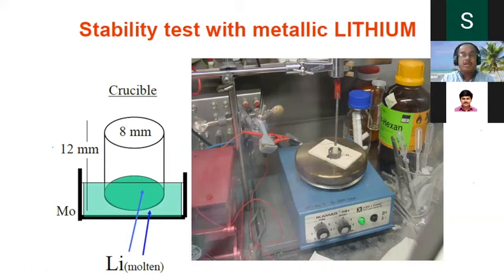So what happened is, when I put the pellet of the bismuth doped system in the molten lithium, it started to creep through the pellet and sit on the top, broke into four pieces, and a big fire took place in the glove box. Very big. I still have the video, wonderful fireworks. Which tells me that bismuth is not stable. Then antimonide is also not stable. Niobium is not stable. Then the tantalum substituted material is the only stable one.